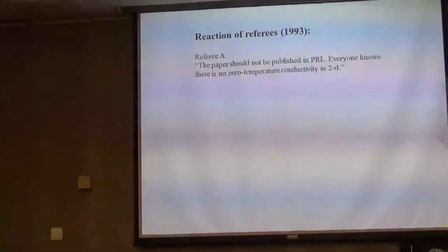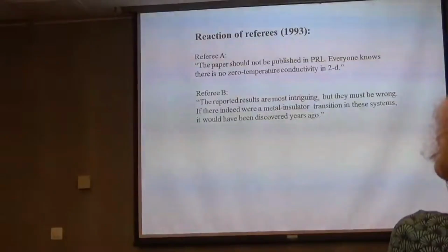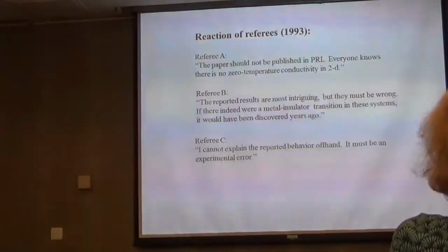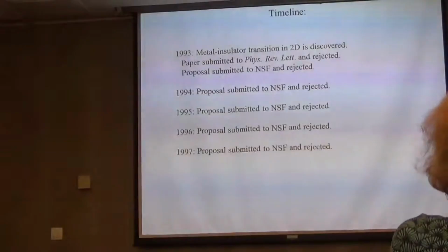And as I promised, I will entertain you now. Reaction of referees. The first set of data was obtained in 1993, and we sent it to Physical Review Letters. Referee A: Everyone knows there is no zero temperature conductivity in 2D. Referee B: It's very interesting, but it's wrong. If it existed, it would have been observed a long time ago. And referee C: I cannot explain the reported behavior offhand. Therefore, it must be experimental error. Excellent. And then, of course, the timeline. 1993 discovered, rejected. Proposal submitted to NSF, rejected. 1994 rejected, 95 rejected, 96 rejected, and 97 rejected. Finally, in 97, something happened.